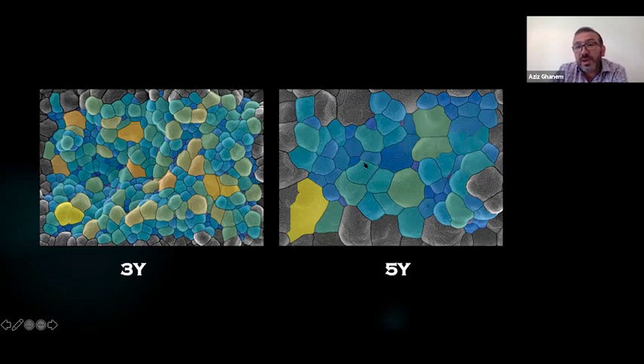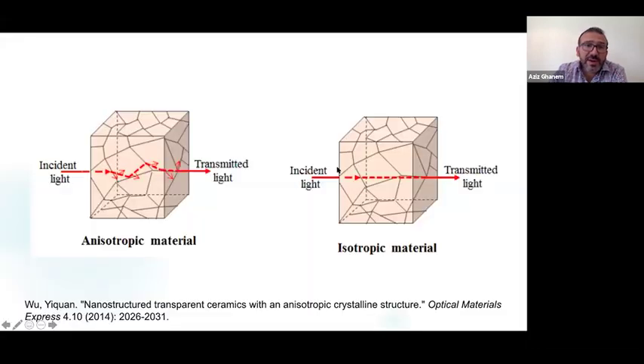Cause light diffractions. However, on the other side, the cubic zirconia has got a larger grain size, and larger grain size means fewer boundaries. So the light would pass more smoothly through cubic zirconia. And this diagram shows you the difference between 3Y and 5Y. So the 3Y, we call it an anisotropic material. So basically you can get different values if you put the light in different directions. And this is mainly due to the arrangement of the atoms and the grains inside the material, which can result in light diffraction. While the cubic phase that we are talking about allows the light to pass without any diffraction, right? So this is all about zirconia at the moment.